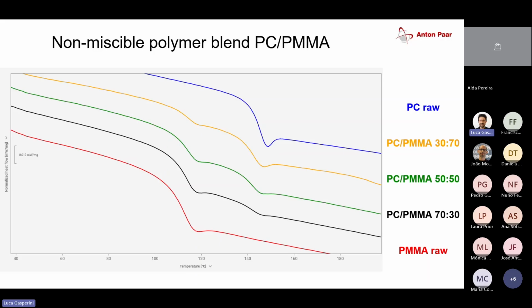But we see that all the blends show us 2 steps in the heat flow curve, meaning 2 distinct glass transitions. Furthermore, we see that the glass transition always happens exactly at the same temperature as that of the neat, individual component that it's coming from. So there's no shift in that. And that can lead us to the conclusion that the PC and PMMA, from the perspective of physical mixing and blending, is a non-miscible polymer blend. Although we have one nice compact material coming out of the extruder, by running the DSC analysis, we can conclude that this is not a miscible polymer blend.